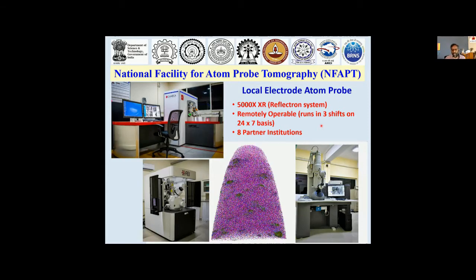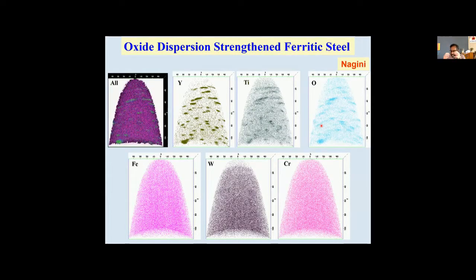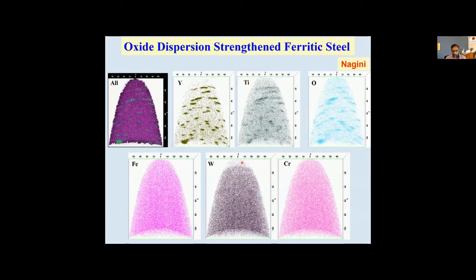This is one sample — an ODS steel, an oxide dispersion strengthened steel in which yttria nanoparticles have been added. I want to know whether these yttria nanoparticles are intact, how they are distributed, and whether any elements are reacting and changing their composition. What I do is take the sample and map each element. You can see iron mapping in pink, then tungsten and chromium — this is a 9-chrome 1-moly 1-tungsten type alloy. Iron, tungsten, and chromium are all uniformly distributed. But if you look at yttrium, titanium, and oxygen, they are distributed only in those particles, and each particle is 2 nanometers. In a 2 nanometer particle, you can actually see which atoms are where — that is an amazing technique.